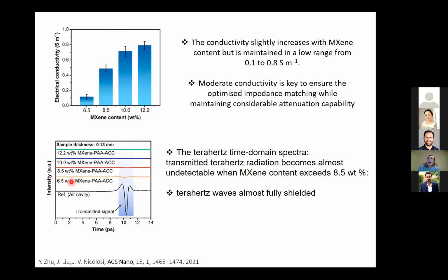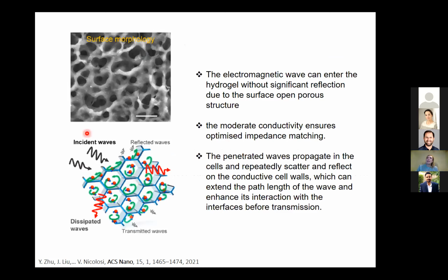So, for example, here is the radiation in the terahertz domain of an unshielded signal. Here you can see that already after adding 6.5% of MXene in this hydrogel, you can shield most of the radiation. And with 8.5% of MXenes, you've completely shielded the terahertz spectrum. So this was quite promising. We believe that this shielding comes from this beautiful porosity that we get. So the radiation gets in, and then it gets reflected several times in the cavities, and then eventually gets dissipated, and the transmitted waves are really dimmed down.